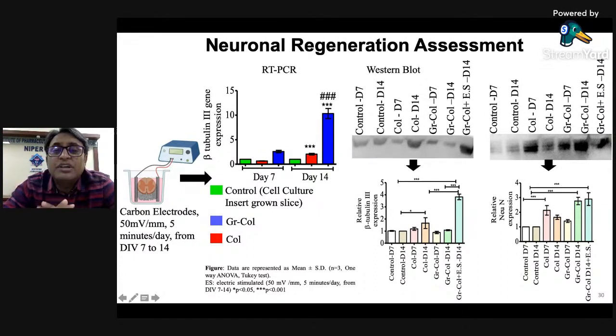However, it is also seen that at the PCR level, a lot of mRNA is forming, but at the Western blot level, in GR col at day 14, beta tubulin is very high, yet the NeuN expression is not so high - almost similar to the unstimulated sample. But overall, the conclusion is that the material along with the current promotes neuronal regeneration much better than the collagen hydrogel alone.